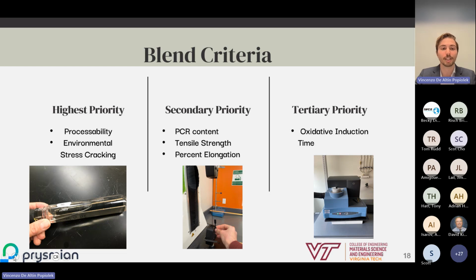So of highest importance, we deemed processability, as the Prysmian group needs to be able to run these polymers and these blends on their lines, maintaining a similar throughput without having to change the conditions on their lines too drastically. Next was environmental stress cracking, as this is one of the more common failure mechanisms seen in the field and something that is harder to change as there are no additives you can add to improve this, and thus is something that needs to be designed for more actively.